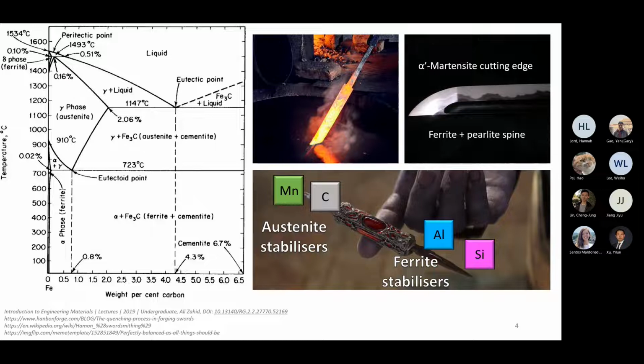And these austenite stabilizers, ferrite stabilizers, they affect things like your austenite stability, so stability against transformation into martensite, and also things like stacking fault energy, which affect the TWIP effect, and I'll talk about that later. So really, depending on the type of mechanisms or plasticity enhancing mechanisms you want in your steel, your austenite and ferrite stabilizers have to be perfectly balanced, as all things should be.